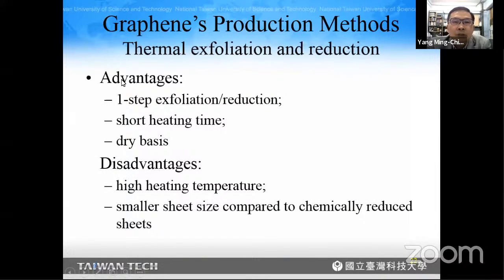The advantage of this method is, first, it is a one-step exfoliation and reduction, and the heating time is short, only 30 seconds, and this is also dry basis because there's no solvent involved. The disadvantage is we need a high heating temperature, and the other one is a smaller sheet size compared to chemically reduced sheets.